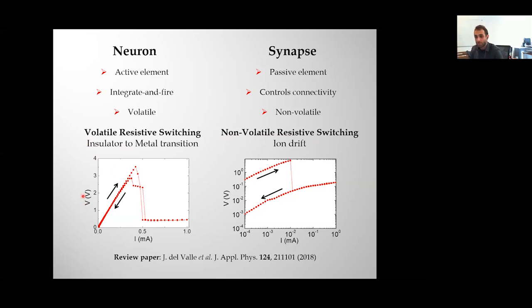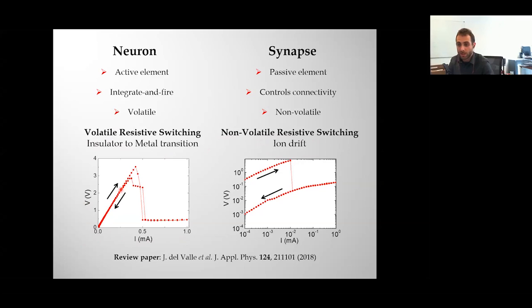And here you have the examples. So this is voltage as a function of current for volatile resistive switching. You apply a stimulus, a voltage or a current, and past some threshold, you can make the material become conducting, and when you remove the voltage, it goes back to the insulating state. So this looks a lot like what a neuron should do. And on the other hand, you have this non-volatile resistive switching in which you apply an electric field, you change the resistance, but when you go back, you don't go back the same way. So you have a memory. That's what a synapse should do.